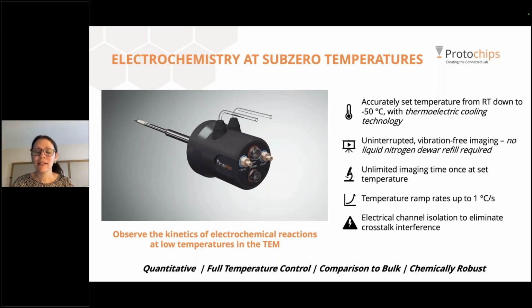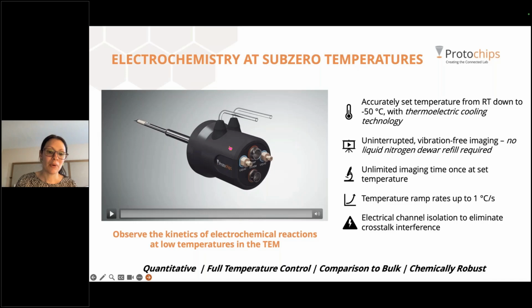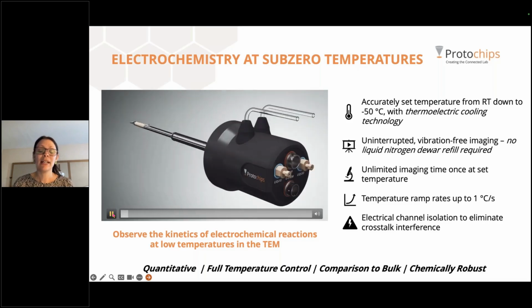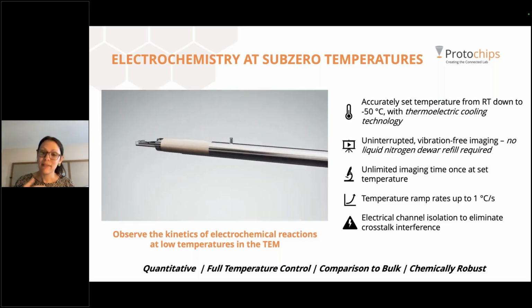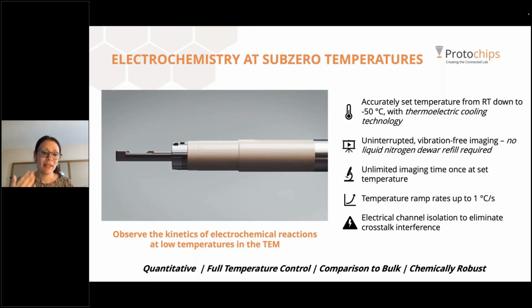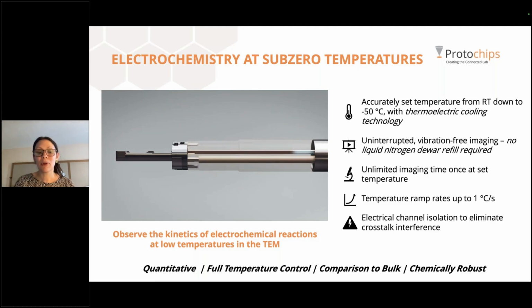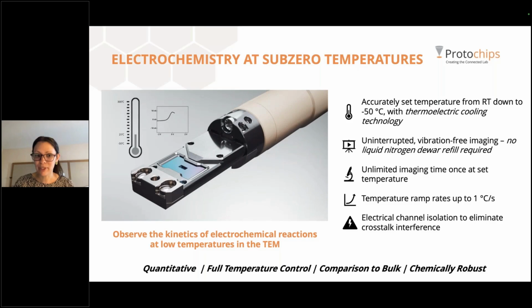Now, from the cooling aspect, we do cooling a little bit differently. This isn't a cryo holder, keep that in mind. We're not trying to freeze the liquid. We're trying to create cooler environments. And so we are using a Peltier device for cooling, so a thermoelectric cooler built into the back of the holder. It's going to cool down to minus 50 degrees C, which is your limit, by cooling through the holder, and it cools down the entire tip of the holder.